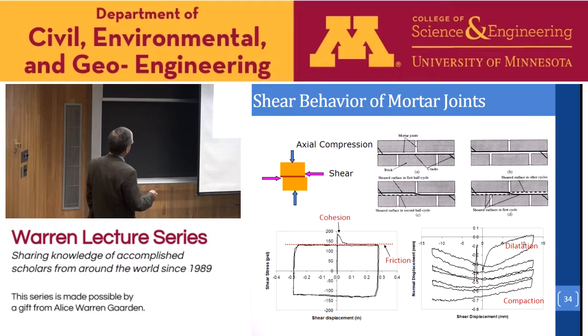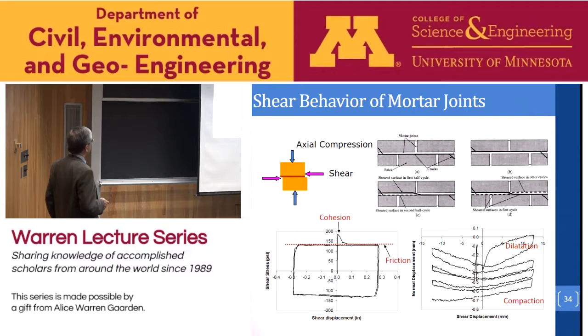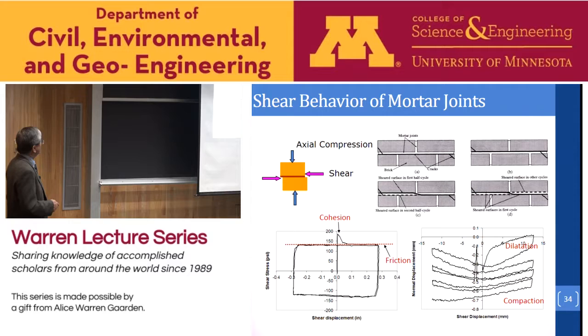So this is really a model similar to what I presented before on the shear key analysis, the interface model for cohesive crack. Now, in brick masonry, the behavior of the mortar joint is a major component, okay? So when the masonry is subject to shearing, sometimes cracks could occur at the interface between the mortar and the brick, and sometimes those cracks actually could cross the mortar joint, okay? And if we subject it to cycles, the shear stress versus shear displacement relation typically looks like this. It's very similar to the behavior of concrete or rocks subject to shear. We start with some cohesive force, and when the fracture occurs, the cohesion will be lost, and then the resistance is essentially by friction.